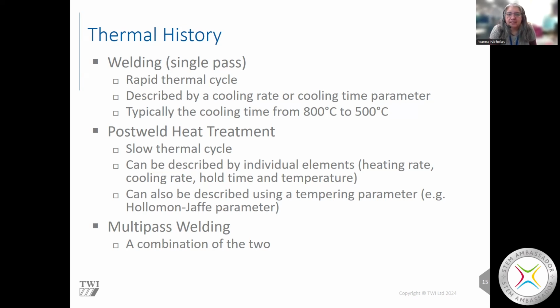But after we completed our welding, we might do some post-weld heat treatment, PWHT, which is a slow thermal cycle. Everything's heated up very slowly, held at a particular temperature for an amount of time based on how thick the material is, and then allowed to cool down. Those different elements, the heating rate, the hold time, the hold temperature, the cooling rates, can be separated out or can be combined into a single tempering parameter, something called the Hollomon-Jaffe parameter, which is often used.